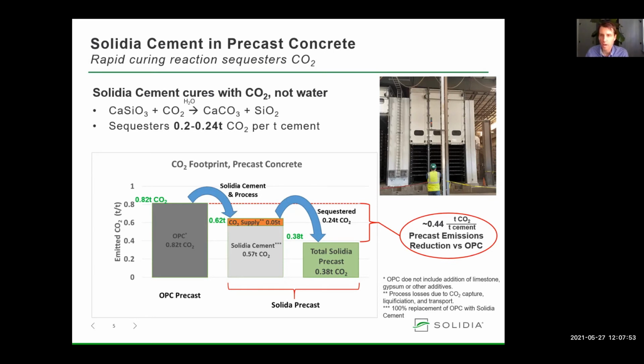The waterfall chart at the bottom of this slide shows a comparison of the CO2 footprint of precast Solidia concrete to precast made with OPC concrete. Starting with OPC at the left with a 0.82 tons of CO2 footprint, there is a reduction in emissions as we switch to Solidia cement. We also include the emissions associated with the high purity CO2 supply that we are currently using, shown in orange. Roughly 200 kilograms CO2 emitted per ton of CO2 captured, liquefied, and transported to the end-use location.